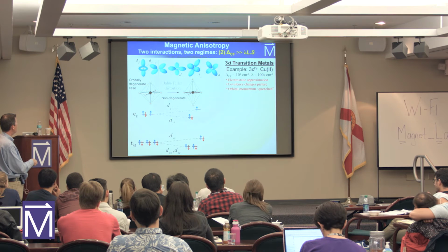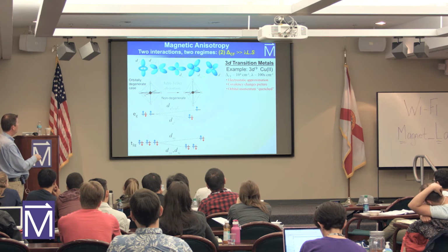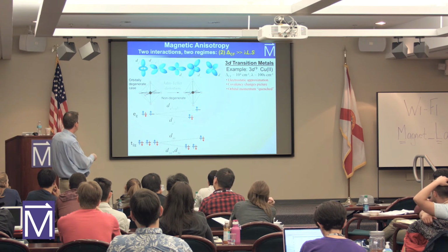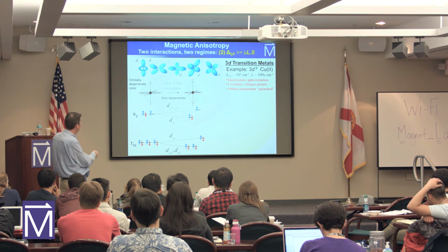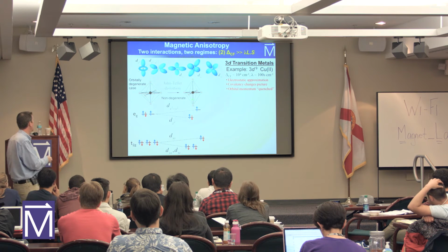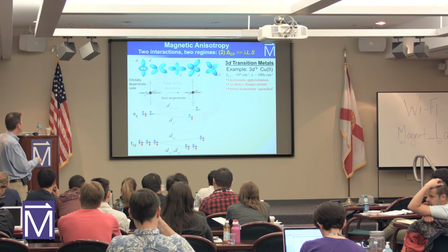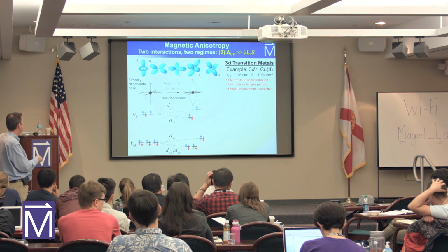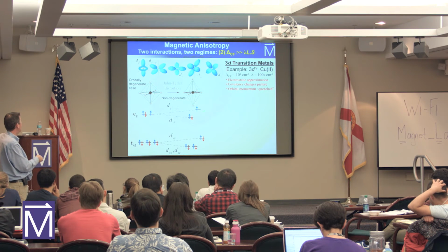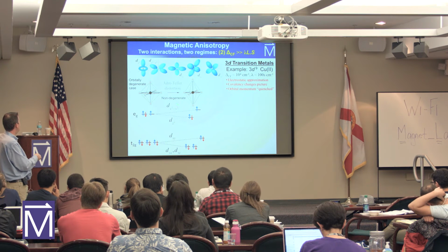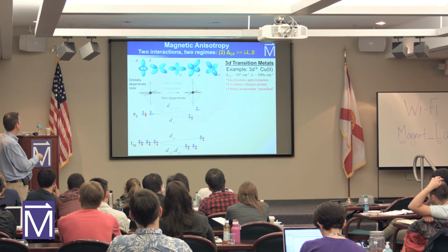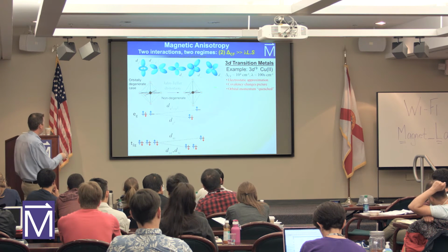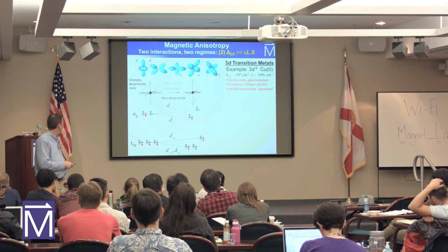And nature doesn't like degeneracy, so it will typically distort, something called the Jahn-Teller distortion. The molecule distorts, or the atom, whatever it is, it could be a lattice or it could be a molecule, distorts in such a way that it lowers the energy of the state that has the 2 electrons in, and it saves energy that way. And now you have just 1 electron left over in this dx squared minus y squared orbital, the one that sits in the plane of the distorted octahedron.